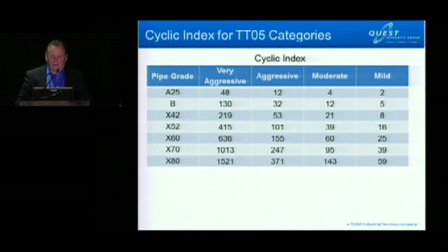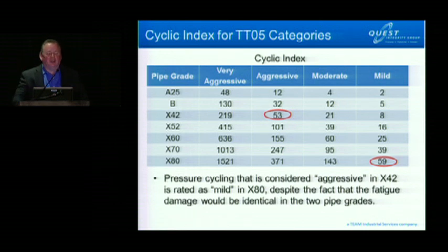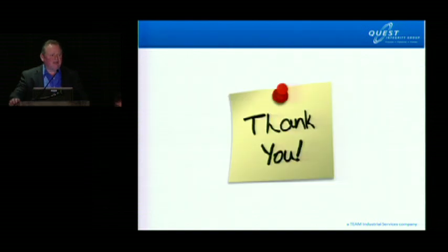And you see that the cyclic index, which is based on absolute stress, varies significantly with the pipeline steel grade. So for example, you see the 2 circled numbers. Under X42 aggressive, you have a number of 53, and under X80 mild, you have a number of 59. So those numbers are pretty close. So what it's saying is if you have the identical cycling in an X42 pipe and an X80 pipe, in one case you consider that cycling mild, and in the other case you consider it aggressive. And it's the same exact cycling, which will produce the same exact fatigue damage. So this is an alternative to that. And I believe that's my last slide, so thank you very much.